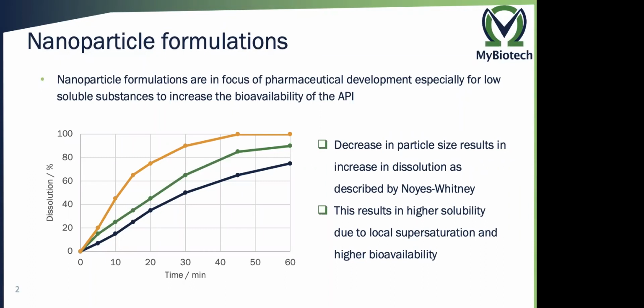What happens in the dissolution of nanoparticles? Obviously, decreasing the particle size results in an increase in dissolution, based on the Noyes-Whitney equation as described years ago. So smaller particles dissolve faster. There's also one add-on: the higher solubility comes with higher dissolution due to the local supersaturation of the nanoparticle formulation. They shortly reach a supersaturation that is higher than the solubility of the API in the medium, and as a result we have higher bioavailability in oral formulations.